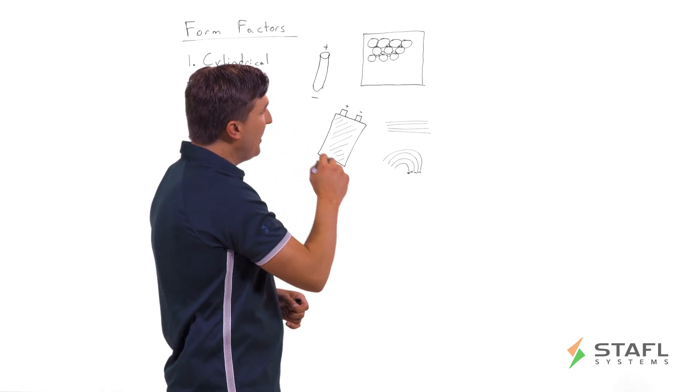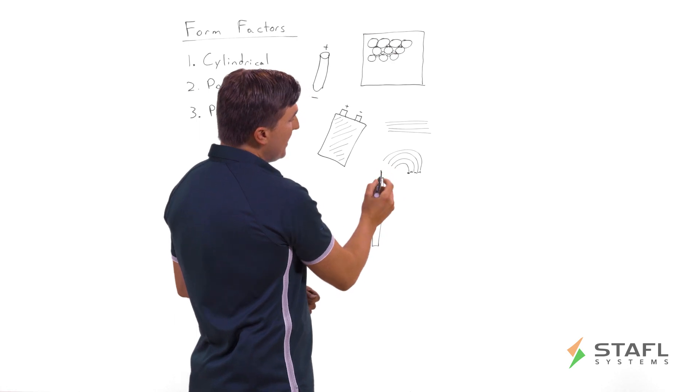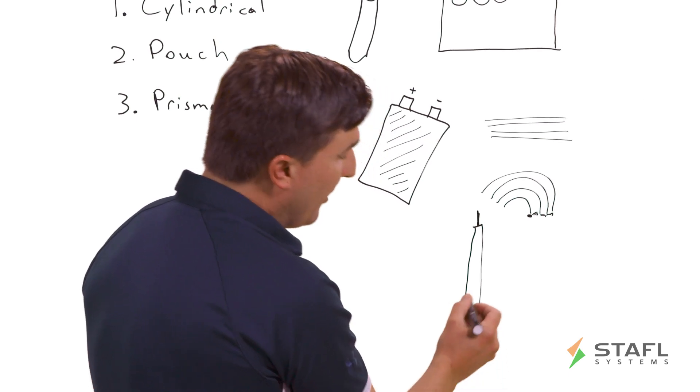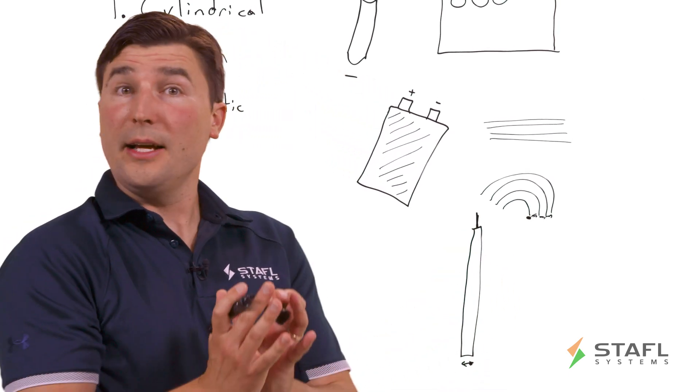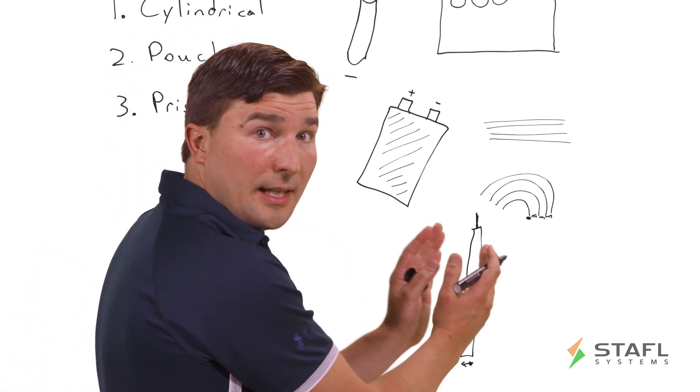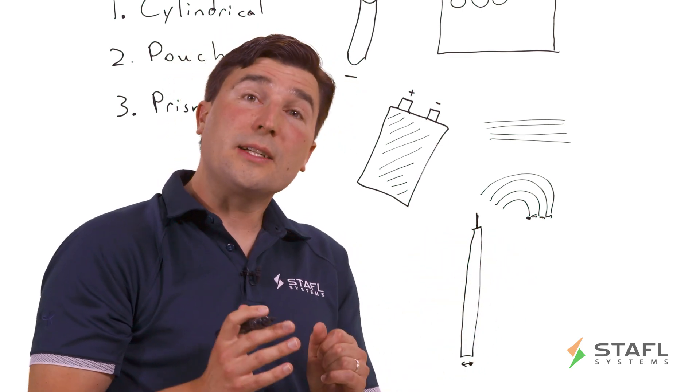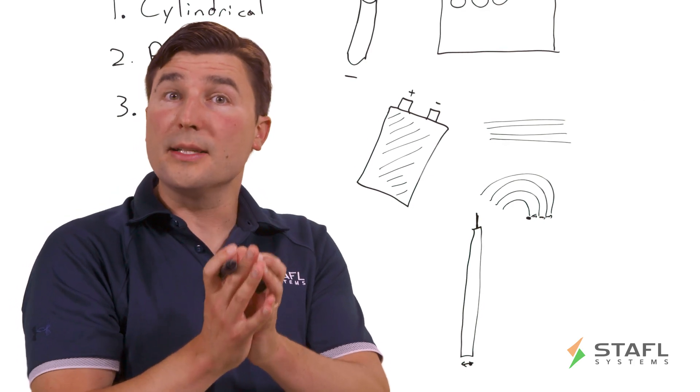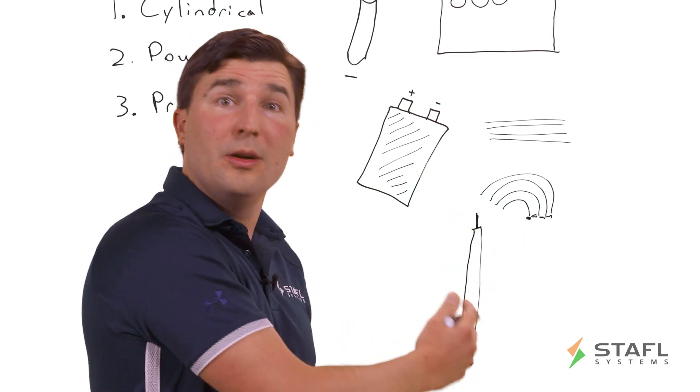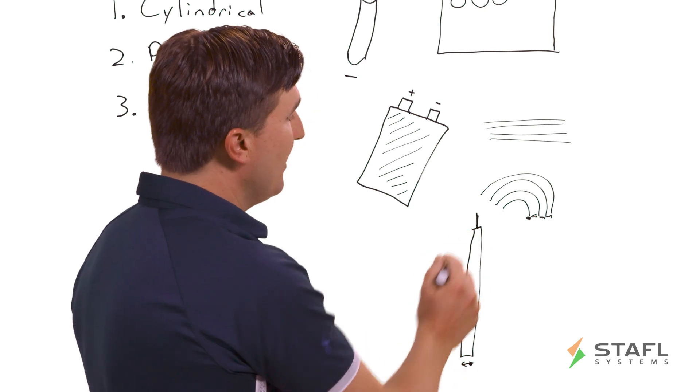Also one thing to consider with the pouch cell is the thickness of the pouch cell. So this is a side view. The terminal is on top. The thickness here will actually vary over the charge and discharge cycle and the lifespan of the cell. Generally speaking, you're talking about six to seven to eight percent expansion and contraction in terms of thickness. It doesn't sound like a lot, but that can actually yield problems when you're designing your cell module architecture. And so it's important to have some sort of compliant member like foam or some other means of accommodating that expansion and contraction for ideal cycle life.